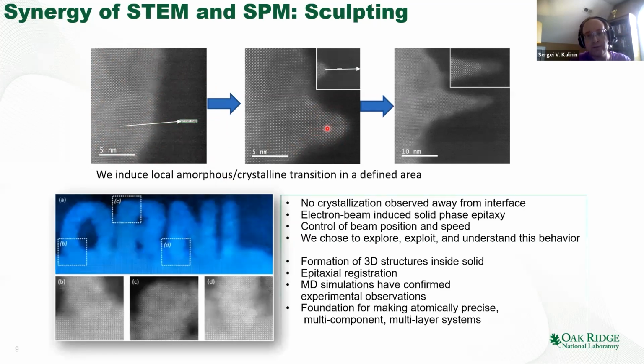And it turns out that this process is controllable enough that if we tell our microscope to scan across the letters ORNL, we'll form these letters. And if we zoom in on it, you can see atomic resolution. So it's almost like 3D printing in 2D. Not 3D, as John showed. It's 2D printing, but with atomic resolution, on the atomic scale.